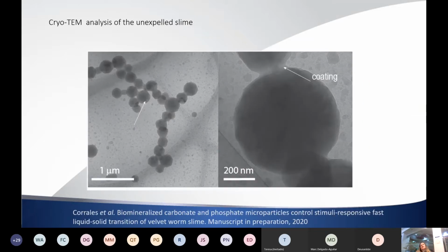And the first thing we did was cryoTEM. We took the slime directly from the animal inside, and also the expelled one. Both are almost exactly the same. And we saw that this slime was formed by these electron-dense microparticles, and even using cryoTEM, we could clearly see them. So they are not an artifact because they were inside the animal and outside, and also in cryoTEM conditions that simulate the natural liquid environment.